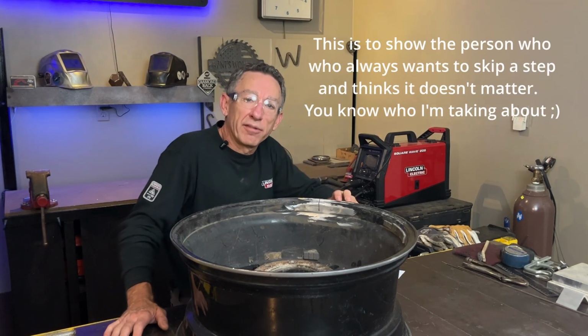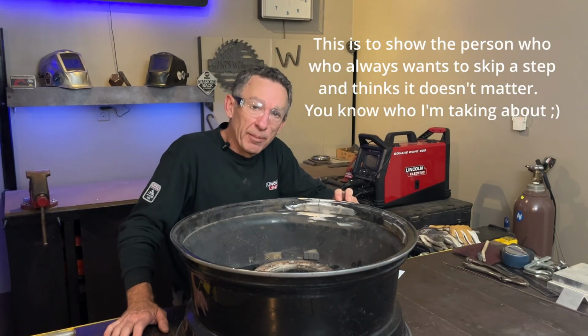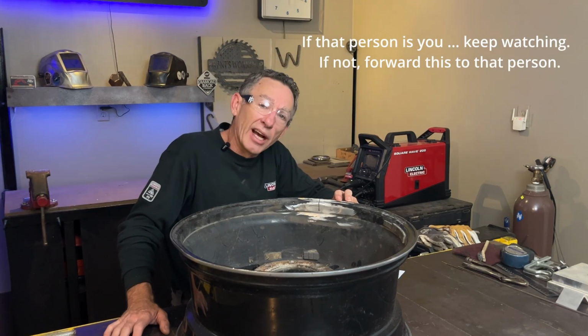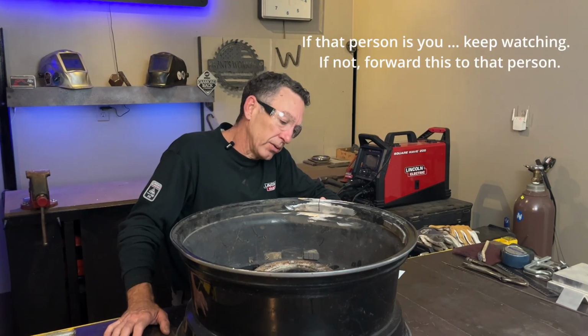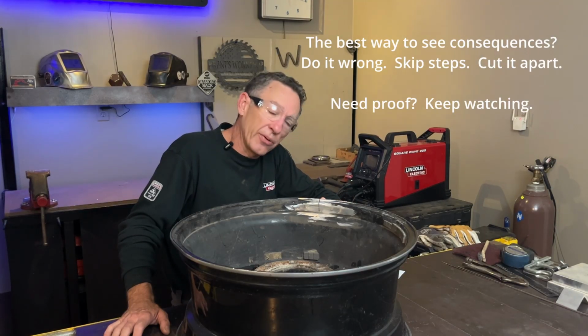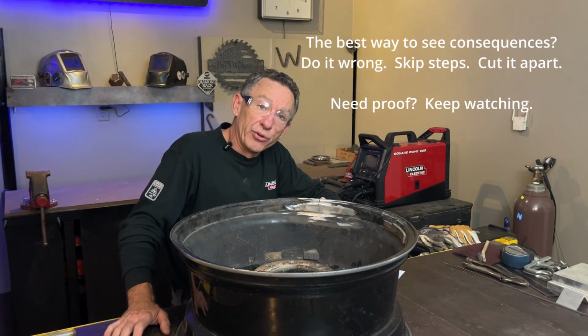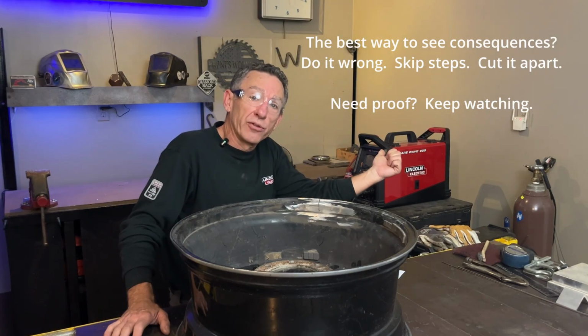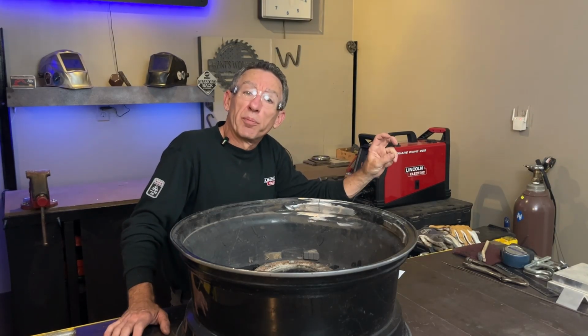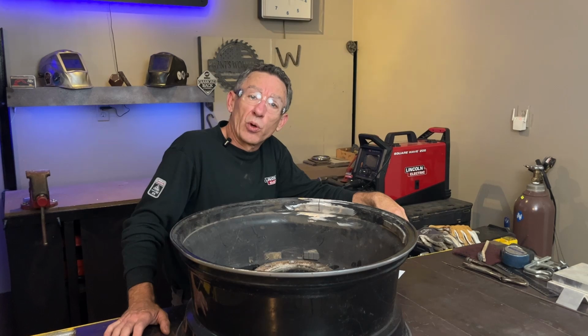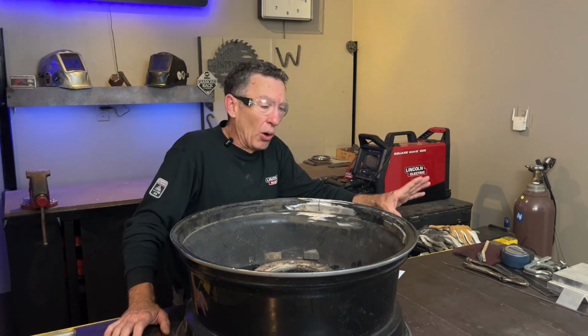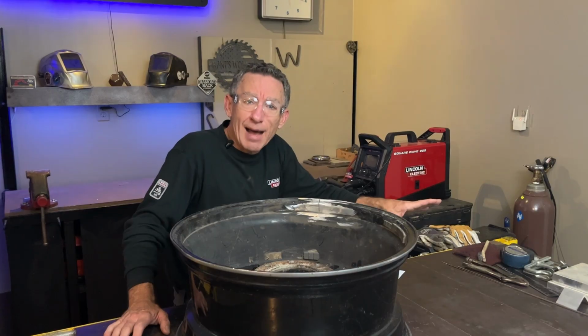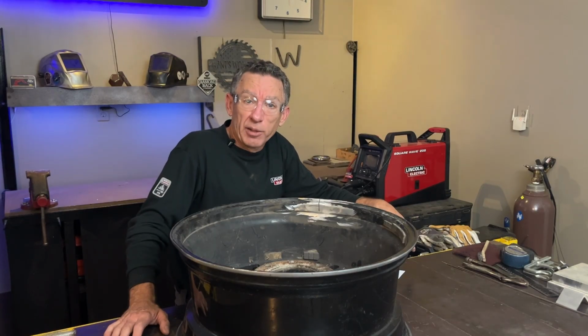So after all that, I'm going to do something different. I'm not going to preheat it, and I'm not going to degrease it. I've got it cleaned up pretty good. I cut right down through the center of that weld, got rid of all the trashy material around it, and what I'm going to do is use the arc cleaning action of the Lincoln Square Wave 205, set with the balance just a little bit lower than I'd like to run, and let that clean and eat through the oxide. And if I see that it's pulling a ton of trash out, I'm going to stop and continue with my cleaning process.